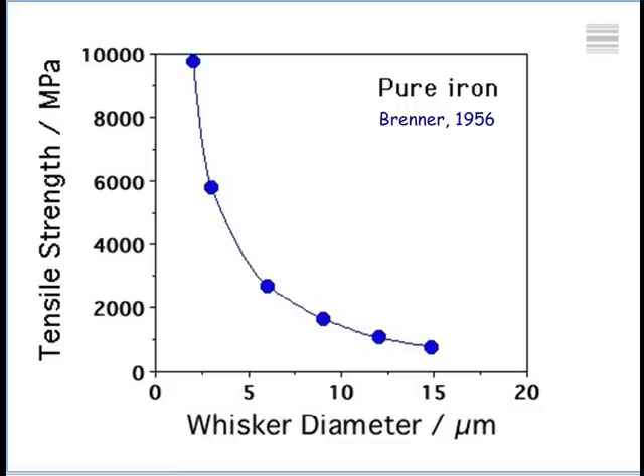And you could actually go to 22,000 megapascals, theoretically. Okay? Now, one problem with this is that the strength collapses as I increase the size of my piece of steel. And the reason is that this relies on perfection for strength. That means if you make a perfect crystal of iron, it will be very strong because it doesn't contain defects. As soon as you make it larger, thermodynamics tells you that there are necessarily defects in the material, and therefore the strength collapses down to values which we are more familiar with. So it isn't good to try and produce strength by making your steel perfect. That means without defects. Because as soon as you make it larger, the strength will collapse.